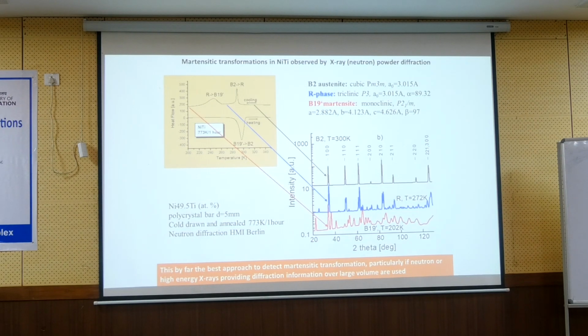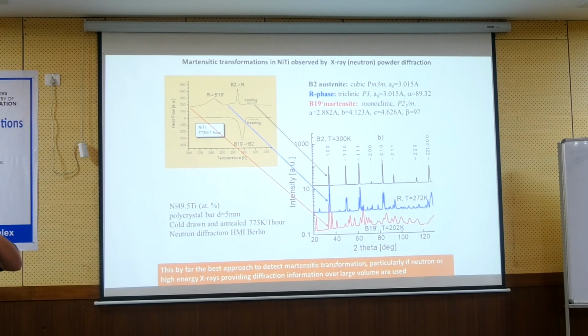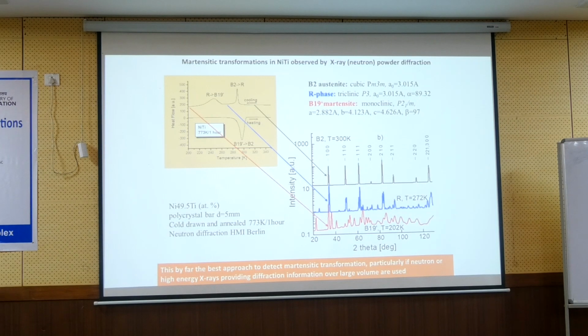not just the surface. So in any trials to stretch the NiTinol and use lab X-rays, you can get something, but you cannot really trust it, because the surface layer could be different than the bulk. The stress on the surface is frequently slightly different than in the bulk. But if you stretch 5%, it's okay. Still, you might have a different condition on the surface than in the bulk. So these high energy X-ray or neutron experiments are more suited for in situ loading.